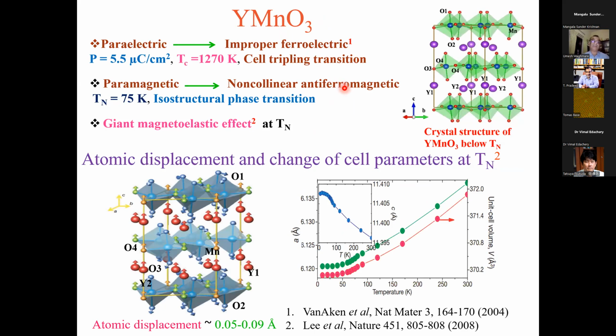It's an interesting material. At fairly high temperatures, below 1270 Kelvin, it becomes ferroelectric. It's an improper ferroelectric. I won't go into those details, but this involves a cell-tripling transition. And as you lower the temperature, at much lower temperatures, at 75 Kelvin, the Néel temperature, it becomes antiferromagnetic, meaning the manganese spins align in a certain way, which is not parallel to each other. And also experimentally, Sang-Cheong's group at Rutgers reported a giant magnetoelastic effect at the Néel temperature, which involved displacements of atoms, which are shown here by these arrows.